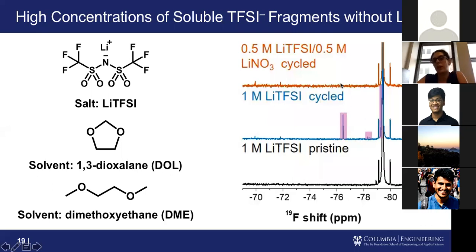And then in blue, I'm showing 1 molar LiTFSI after 100 cycles. And then I'm showing 50-50 TFSI lithium nitrate after 100 cycles. So in both cases, you get these little mini decomposition peaks out here. But what's most noticeable is that you get these larger decomposition peaks that are fragments of this CF3 from the TFSI that are highlighted here. So this is quite a high concentration of salt decomposition product when you don't have any lithium nitrate present. And we know that the performance and the plating behavior is much worse in this electrolyte here.